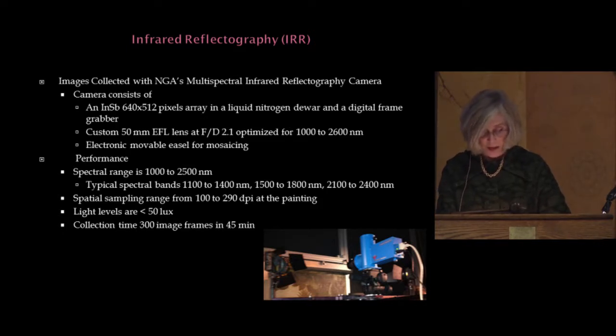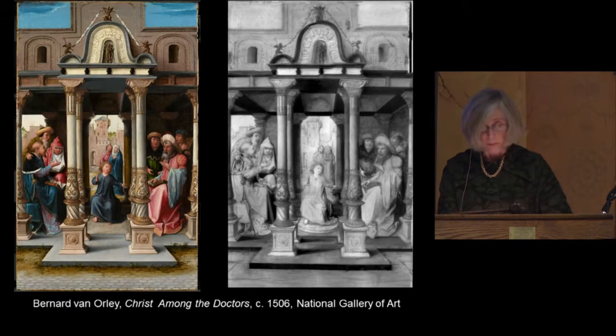These systems were found to improve paint penetration by extending sensitivity further into the infrared range and eliminating geometric distortions that were a problem in the older technologies. The use of passband filters, which allow narrow band wavelengths to pass through while blocking all frequencies outside the set range, has further improved these infrared images, and this research is still ongoing. The images obtained with our present system are extremely clear.